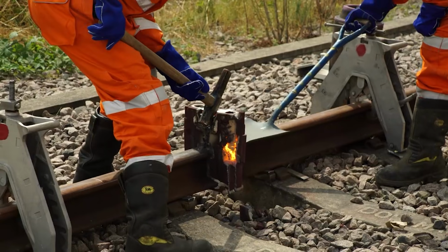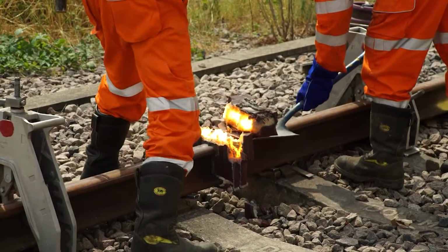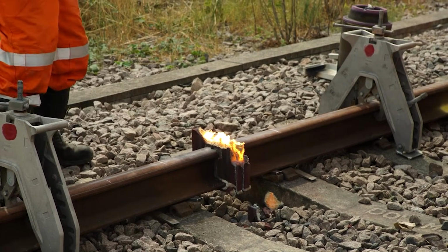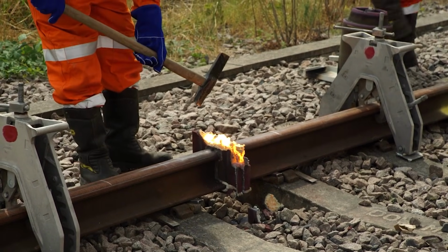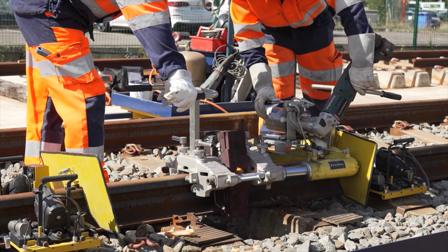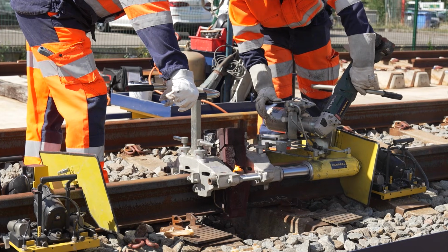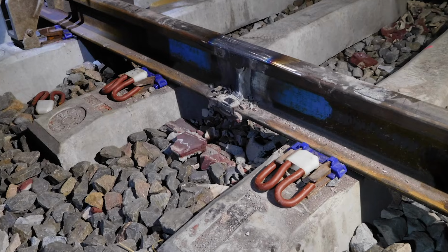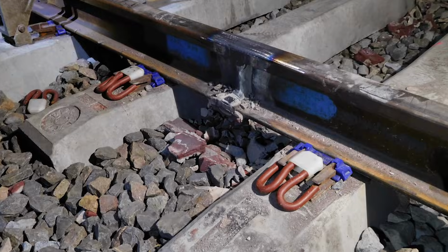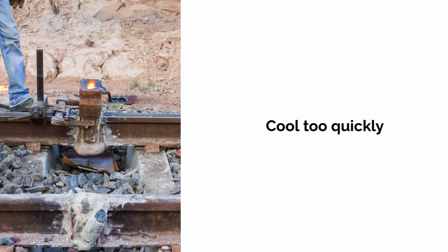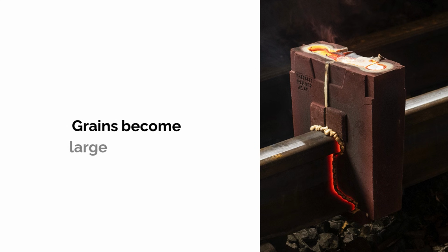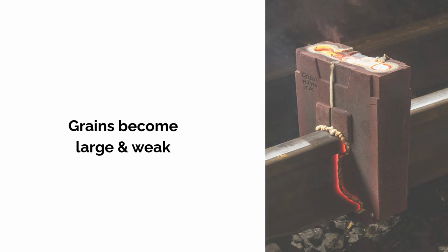The riser and any remaining slag are removed. Excess metal that was deliberately added during the pour to feed the weld as it cooled is now removed using a hydraulic trimmer. As the metal solidifies, its internal grain structure forms. Cool it too quickly and it turns hard and brittle. Cool too slowly and the grains become large and weak. The target is a fine perlitic structure, the same type found in most other railway steels, which gives strength, ductility and fatigue resistance.